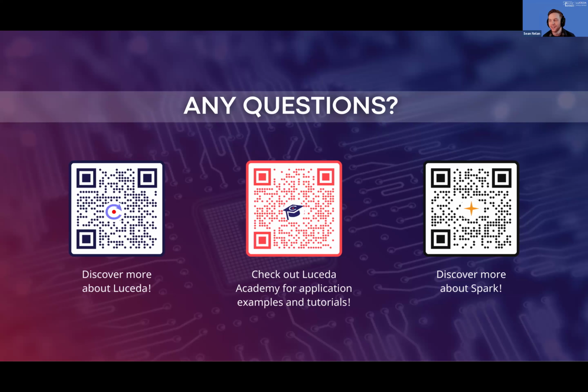Yeah, these are great questions. So this is actually a really interesting one because I would say the emergence of TFLN in industry has really come down to our perfection of the molecular bonding process of that TFLN film. If you look at papers and reports and literature from perhaps the 2010 to 2016 era, you'll see that TFLN films were bonded on top of an SU8 photoresist or a UV15. These are polymers, of course, so they have very low temperature tolerance and high loss. But then people figured out how to bond the TFLN directly to an SiO2 layer, or the amorphous version of quartz.